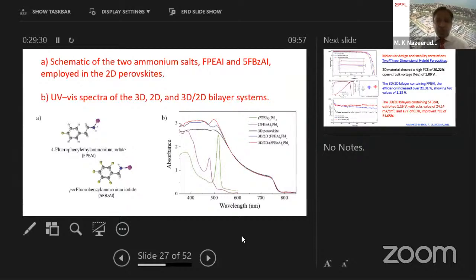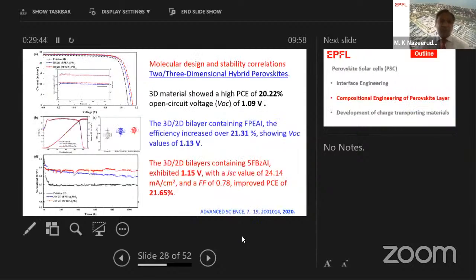The absorption spectra properties are shown here. Again, the two-dimensional perovskite deposited on the three-dimensional perovskite are shown in this curve. So the next slide shows the power conversion efficiency of these materials. So if you look at the A curve, that's our blank, the power conversion efficiency is 20% with 1.09 volts.